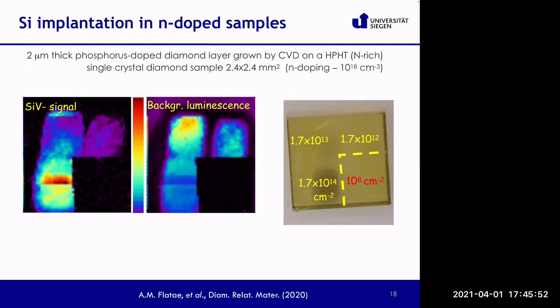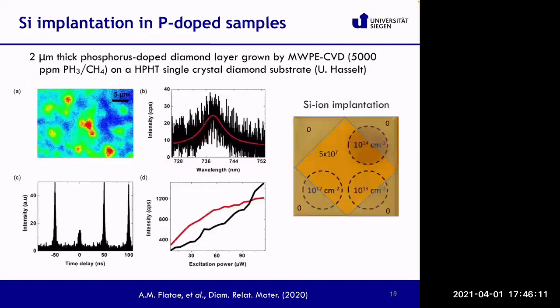And you see that, unfortunately, in correspondence of the single silicon vacancy emission, you have also a huge background luminescence. And this is related, we found out, to the activation of nitrogen, which apparently is co-doping the diamond when you do the phosphorus implantation. But finally, we understood how to get rid of this problem. And in another sample, we managed to obtain single photon emission in a phosphorus doped diamond. So with this result, we demonstrated that it is possible to create a single photon source in essentially semiconductive diamond, which is quite important if you want to get devices for this type of applications.